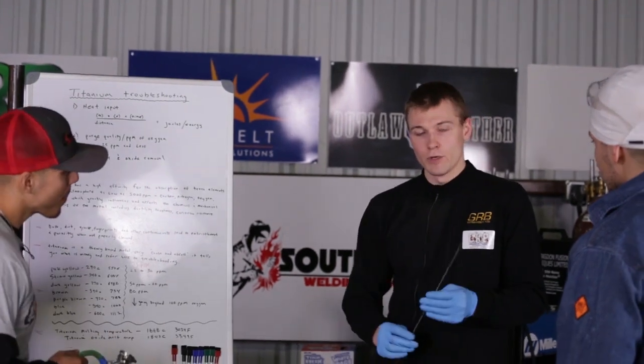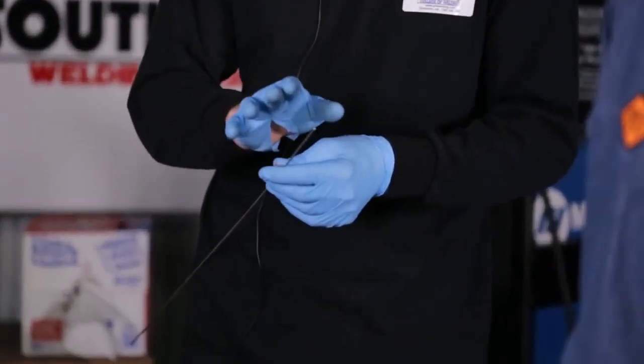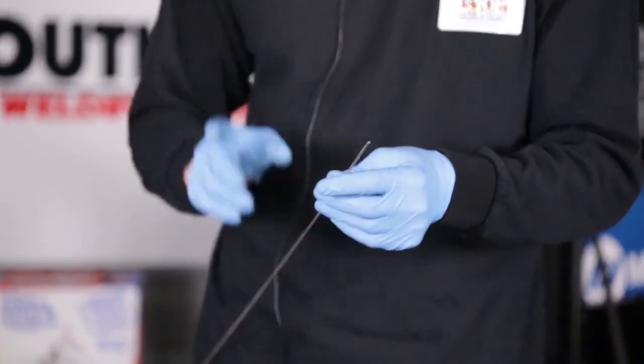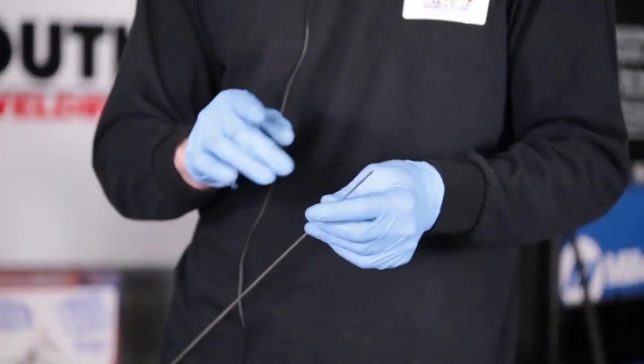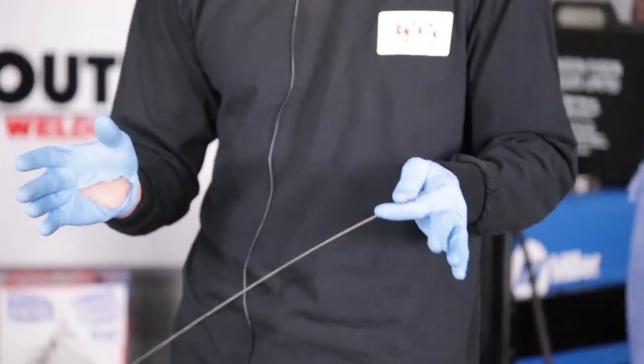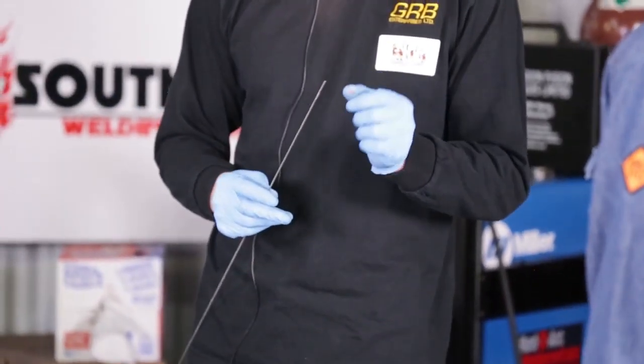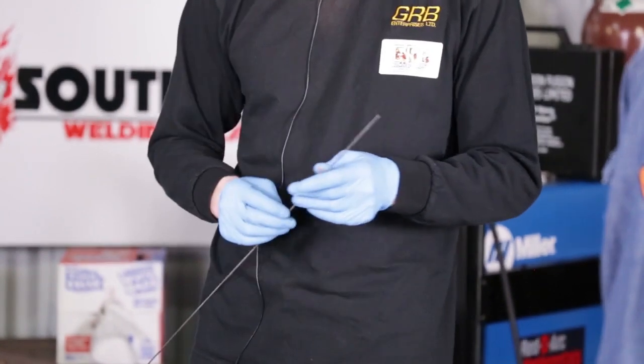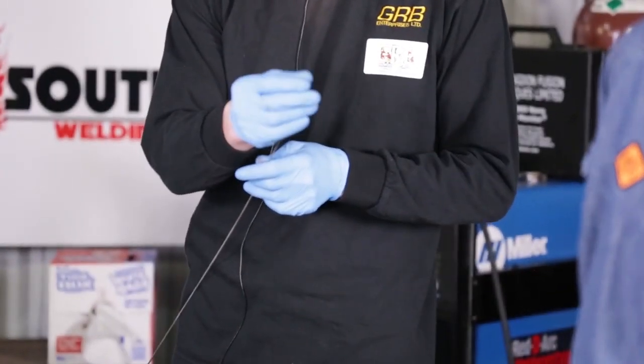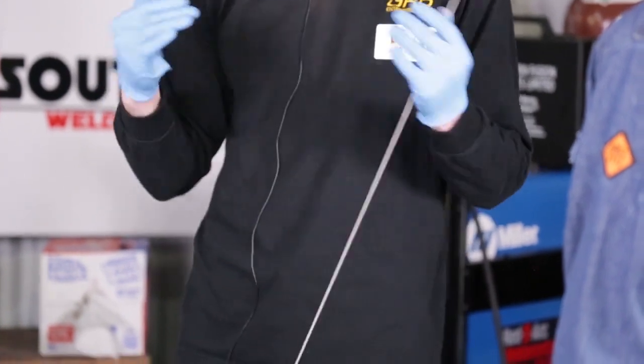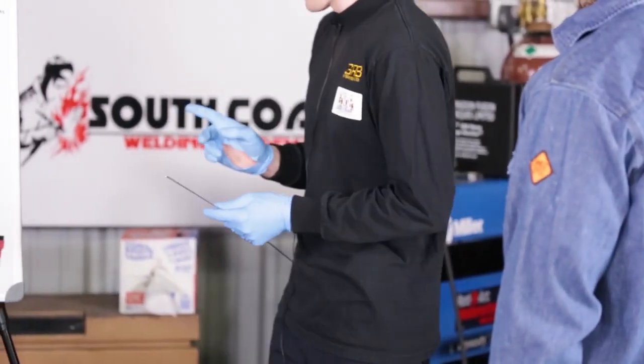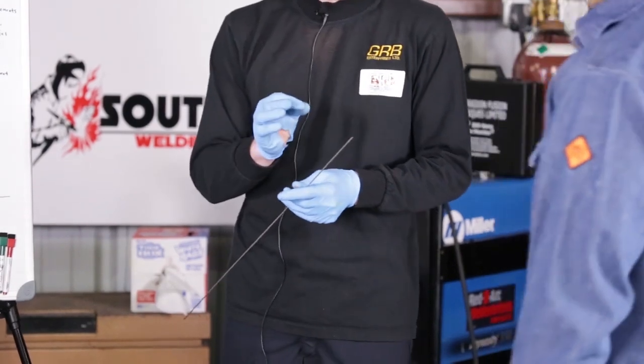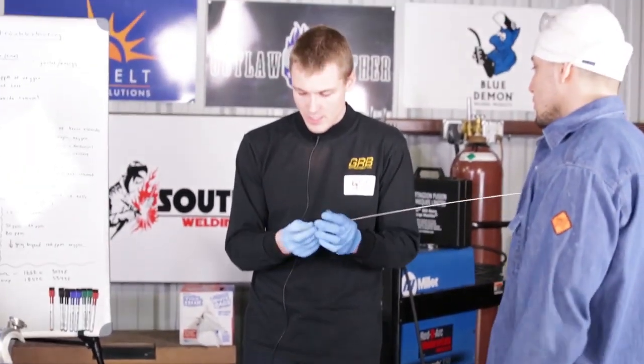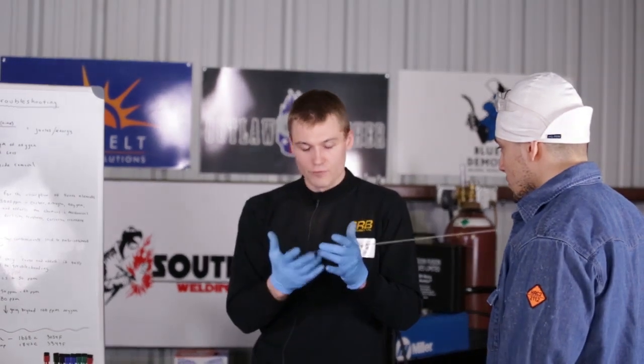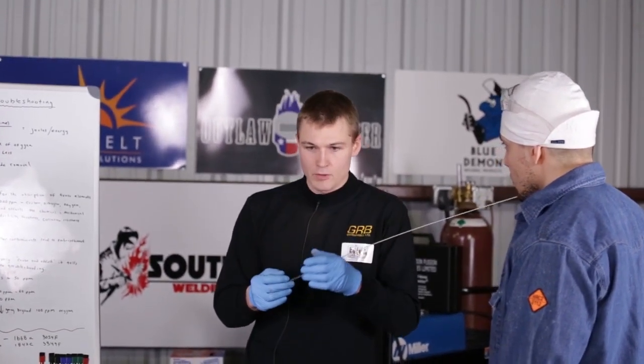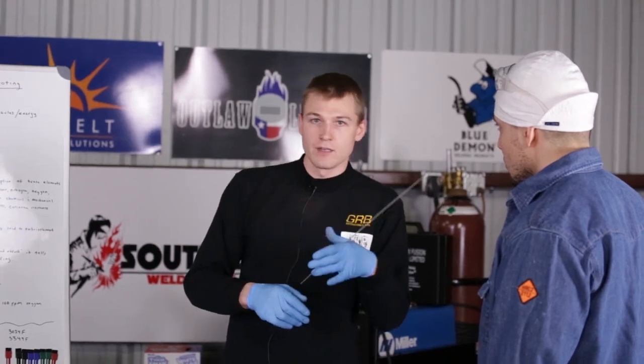Well, the other thing I wanted to include here, and this is another reason why I spent a lot of time at GRB College of Welding with Jerry. I was actually there on the 27th and the 28th of November before I came here with the titanium and aluminum. One of the things I had a problem with was closing the root pass on titanium. Titanium forms an oxide on the tip of the fill metal, especially if it's allowed to interact with the atmosphere. We'll be using a size 12 ceramic cup to do this welding, and the reason why is because when I'm trying to close this fill metal, my mind is trying to dab it to the hottest point, but it sticks all over the place.